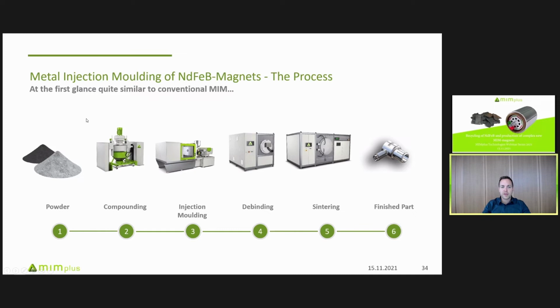First, MIM is a powder-based process. You have metal powder that is mixed with a polymer mixture at elevated temperature to make the so-called feedstock. It's just a mixture in which the metal powder is dispersed, and then you get pellets that can be fed directly into injection molding machines and shaped with conventional injection molding machines known from the plastics industry. Then you get the complex shaped green body, which still consists of 80 to 90% metal powder and 10 to 20% binders.